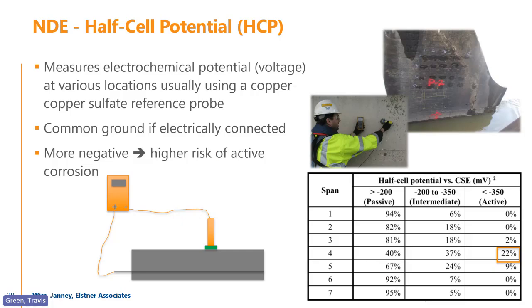Also, just as a warning, I like this technique, but if you have galvanic anodes, if you have spray applied zinc, if you have an impressed current system, this technique won't really work as well, right? Also if you have epoxy coated bar, the technique might not work at all. But in this structure, it had black bar, and we felt pretty comfortable with it.